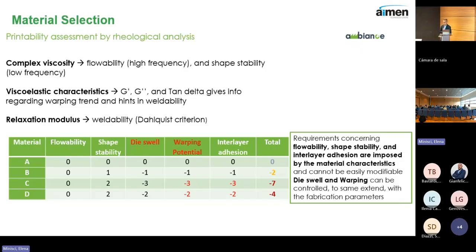Then with the viscoelastic characteristics of the material, so the G prime and G double prime, the storage and loss modulus, and the ratio between them, we evaluate the viscoelastic behavior of the material and how it dissipates stresses. This gives us a lot of information regarding the propensity of the material to suffer warping. And finally, we analyze the relaxation modulus. This is a derived parameter, but by using the so-called Dahlquist criterion, which is very well reported in the literature, we can analyze the potential of the material to provide good adhesion and good part quality.